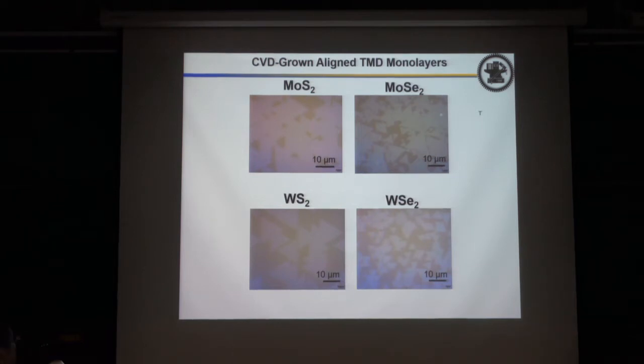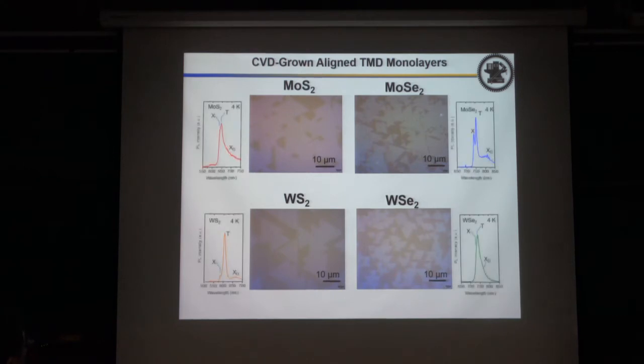So maybe I will show you later the STM result, but here I just show you the low temperature photoluminescence. If you are working in this field, you will know if you cool down any CVD sample to measure the photoluminescence, you will see a very, very strong defect emission, not the exciton emission. But in this case, if you improve the material quality and reduce the defect density, actually the spectrum will be dominated by excitons and a very weak defect emission like this. This is defect emission. This is the exciton. The exciton, very low defect emission. So this is not easy. So typically in CVD samples, the low temperature PL only shows defect emission.